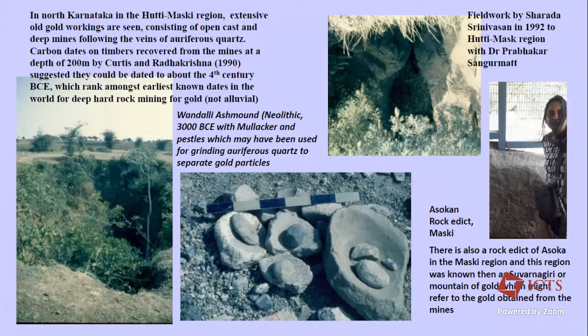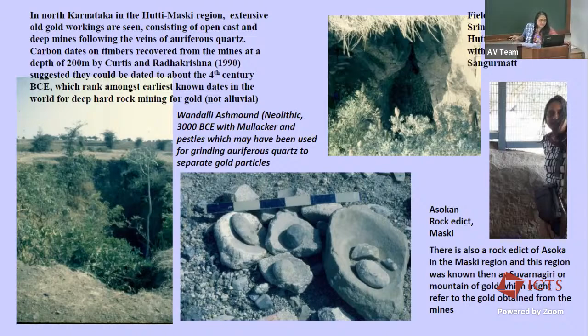And for instance, the Allchins had speculated that perhaps some of the Harappan gold may have also come from these kinds of Neolithic regions. And the other surprising thing was that the dates that were found for some carbon, which were from timbers collected from about 200 meters depth, were already dated to about the 4th century BC. So that is actually slightly pre-Mauryan.